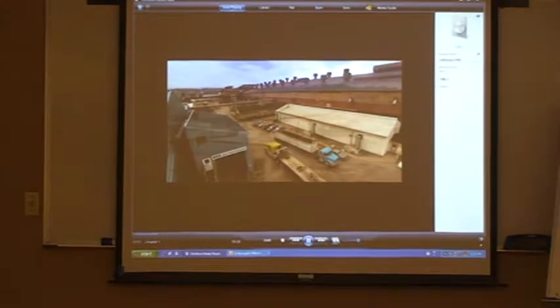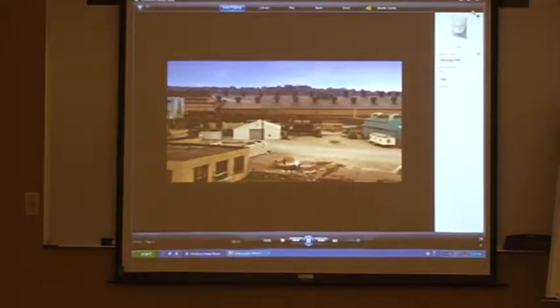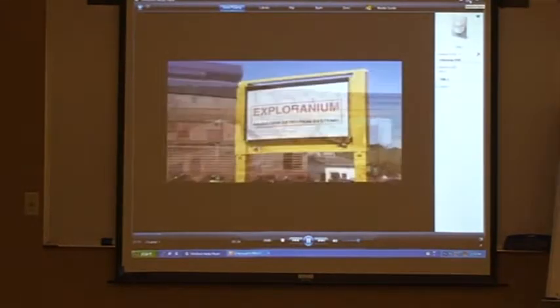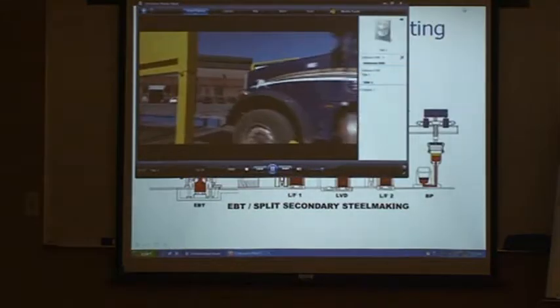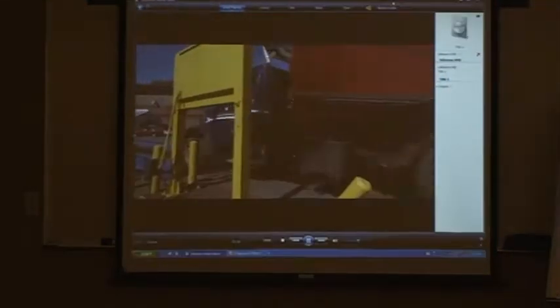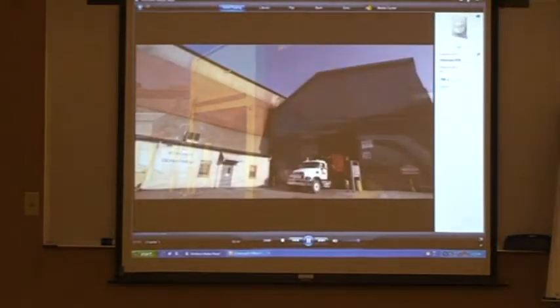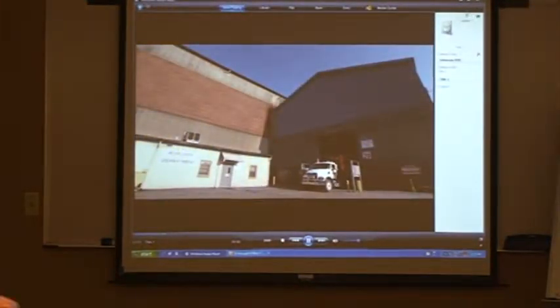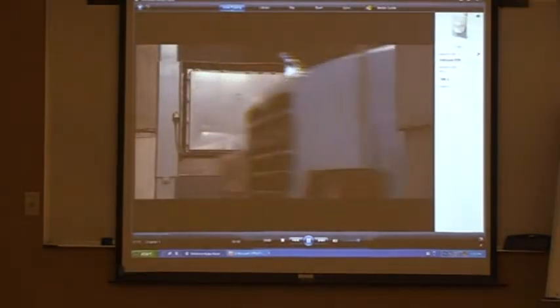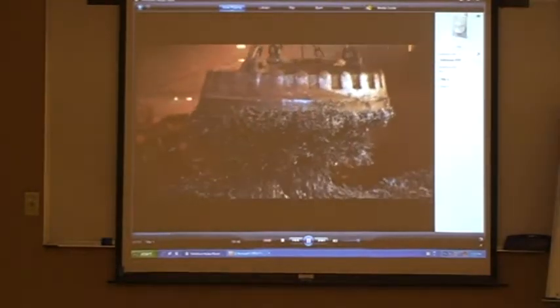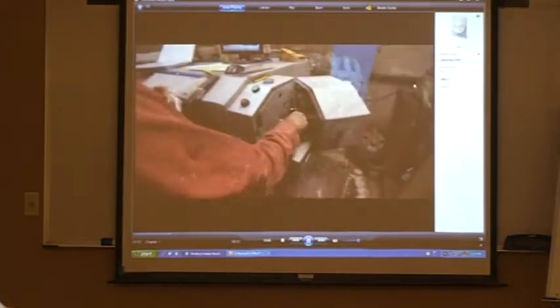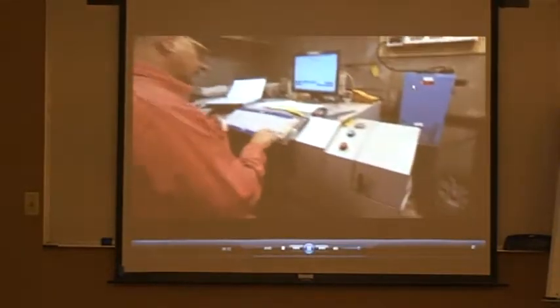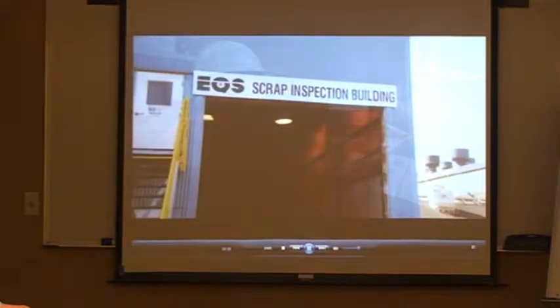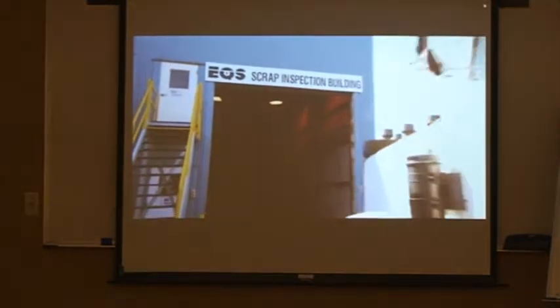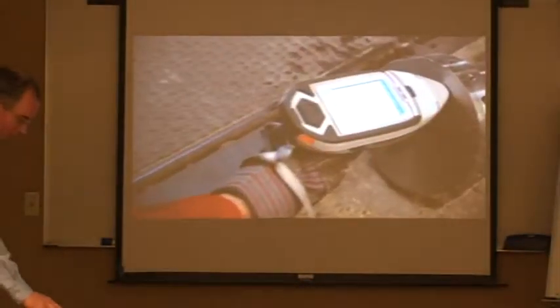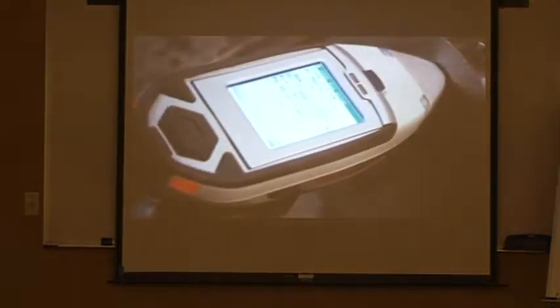Located in Newcastle, Pennsylvania, our steelmaking process begins with the receiving of steel scrap. EOS accepts this material only after it is scanned for radioactivity using specially designed Geiger counters. In addition, there are also radiation checks directly prior to the scrap entering the mill. Before scrap material is charged, and in a chemistry sample taken at the end of the primary melting process, scrap material is also tested for chemistry compliance using a handheld X-ray fluorescence testing device.